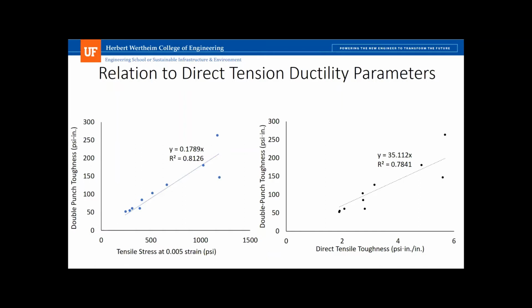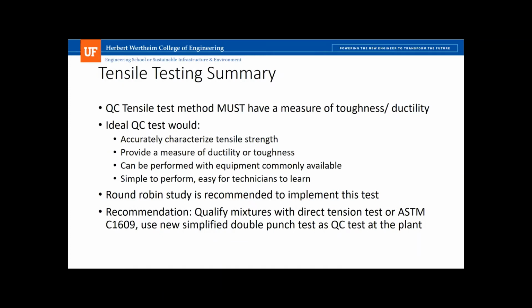These are on the same order of R-squareds as when you compare the direct tension toughness to the flexural result toughness. Very good, nice results. So if we look at a summary of our tests, the first thing we can say is you really have to have a measure of toughness and ductility for UHPC for it to be valuable. Otherwise, a lot of times you're just measuring the first cracking load, or you could accidentally. So for our ideal QC test, looking at our parameters, we find that we can accurately characterize the tensile